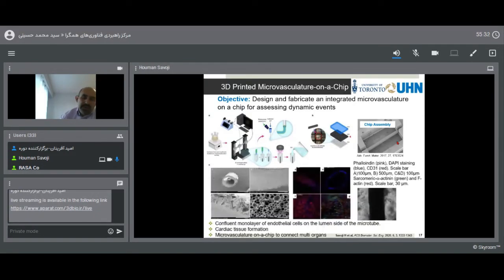this microvasculature. I just want to show you some of the images that we have from the wall of these vasculatures. This is the microvasculature with around 500 micron diameter, and you can see the microstructure of this blood vessel or microvasculature is really porous, so it promotes transferring oxygen, nutrients, and all the other things from inside out or outside in. We also endothelialized this microvasculature, so the endothelial cells can form a monolayer, and later on we form the vascular cardiac tissue around this microvasculature.